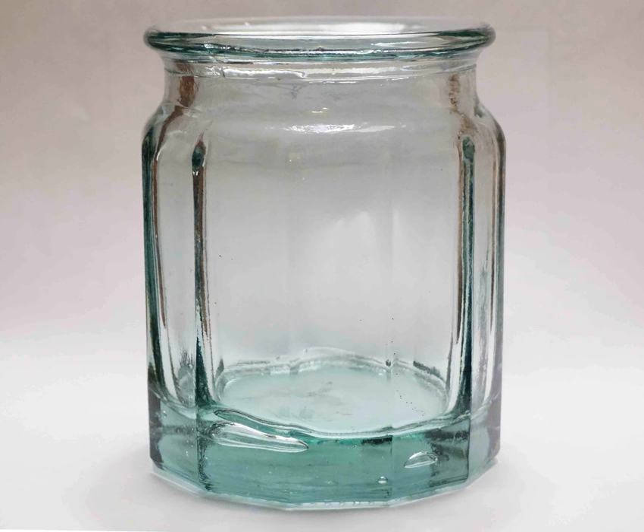Sulfur, together with carbon and iron salts, is used to form iron polysulfides and produce amber glass ranging from yellowish to almost black. A glass melt can also acquire an amber color from a reducing combustion atmosphere. Manganese dioxide can be added in small amounts to remove the green tint given by iron (II) oxide.